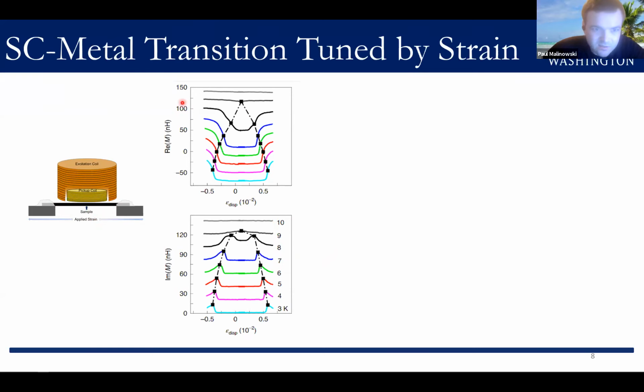So here I'm showing you the real and imaginary parts of that signal as a function of strain. And here each color corresponds to a different temperature. And these are offset for clarity. So looking first at the real part, at high temperature, there's zero signal for all strain, indicating the sample's in the normal state. And then at lower temperature and low strain, there's a negative diamagnetic signal consistent with a superconducting Meissner screening state. And then by applying either enough tensile or compressive strain, we can suppress that diamagnetism.